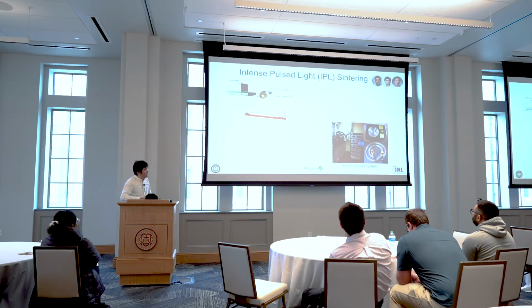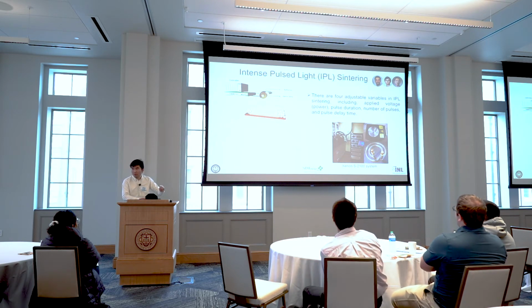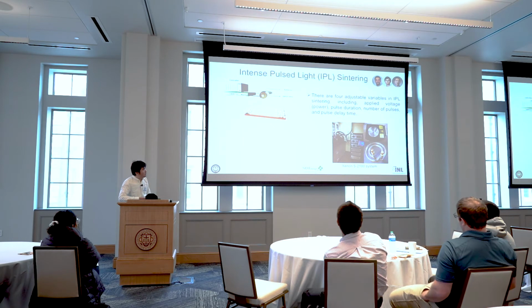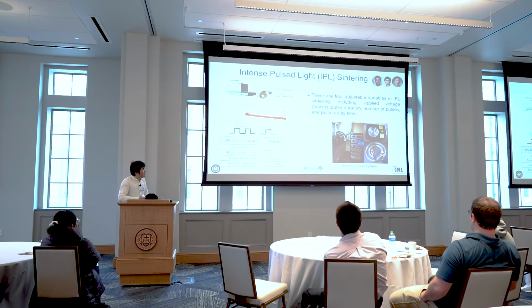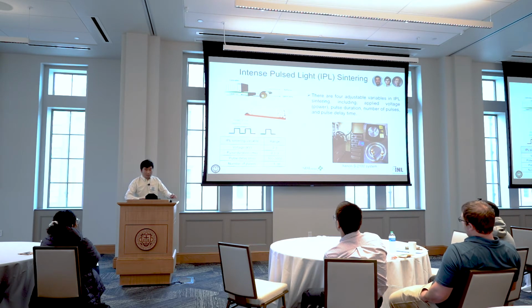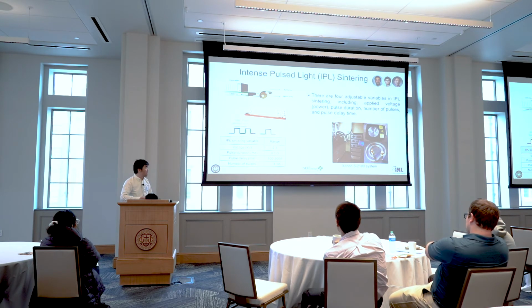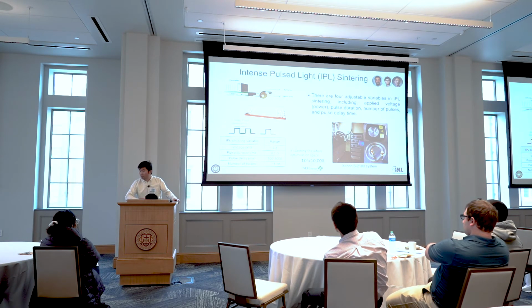Right? So this is a glance of their xenon light, pulsed light sintering system. And there are at least 4 different knobs you can tune on this machine. Okay? And these include voltage, pulse duration, number of pulses, and pulse delay time. It's already a large optimization space, right? So think about if we want to do this in an exhaustive way for optimization, we can take 10 points on each of these parameters, and that quickly builds up to, say, 10,000 experiments that we need to do, right? So this is too large for them to do the experiment, so we hope artificial intelligence will be able to help us.